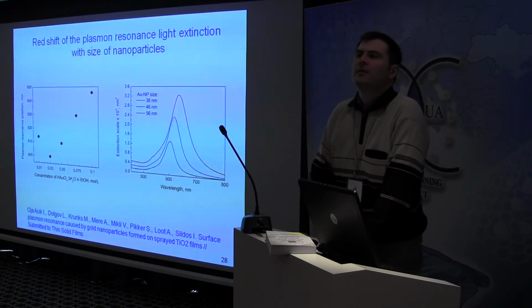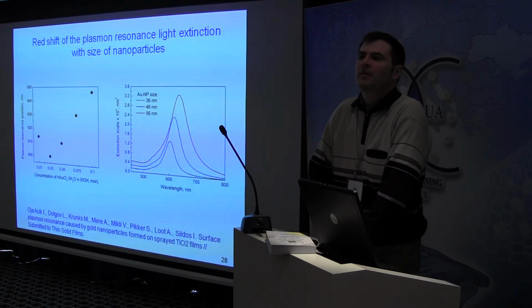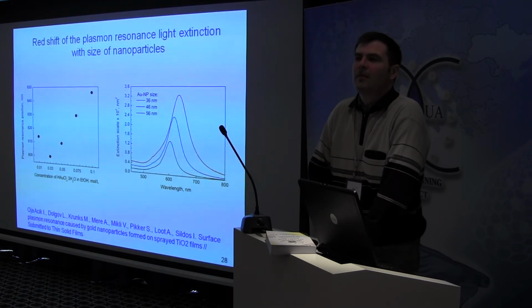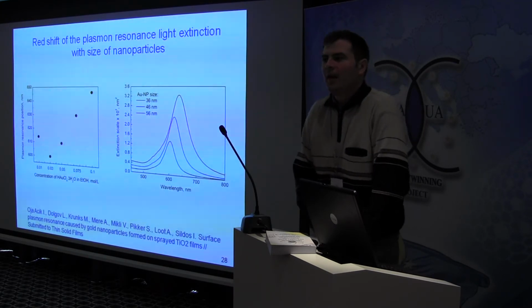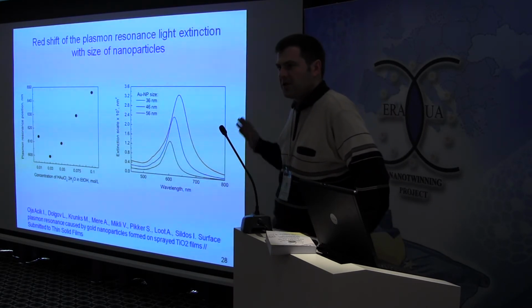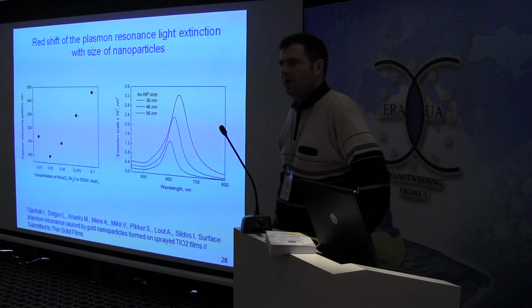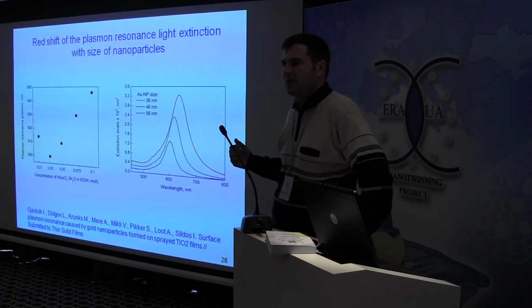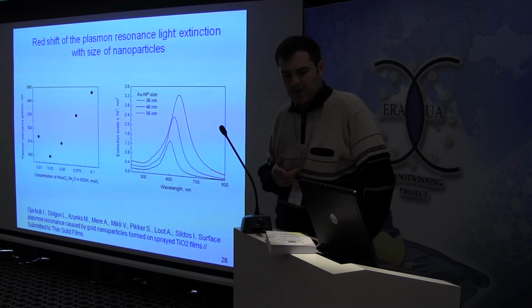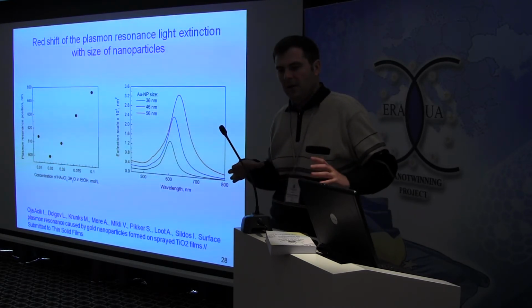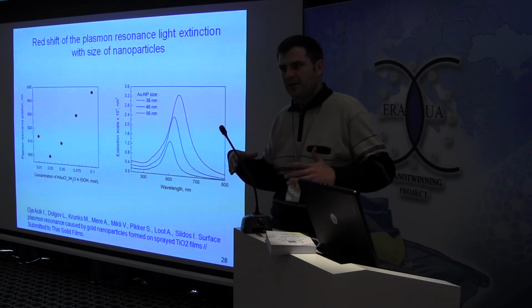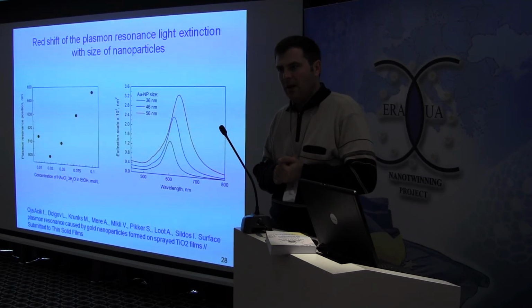First of all, did you notice any agglomeration of your nanoparticles on the surface of your photovoltaic devices? And second, what about hotspots? Maybe the coupling of small nanoparticles would give you an enhancement of the local field, which is known in surface enhanced spectroscopy. Of course, agglomeration can cause such a shift also. I think we cannot say exactly how strongly they agglomerate, but according to SEM images, we did not prepare such very concentrated samples where we have strong agglomeration.